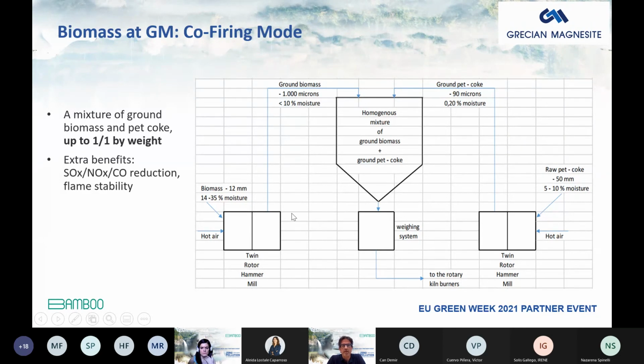Of course, the biomass must be milled in a mill with the introduction of hot air to reduce its moisture. And on the other hand, the pet coke, the unground pet coke, which also has a significant amount of moisture, is also dried and milled. The extra benefit of this partial replacement of pet coke, of course, is the reduction of other pollutants like SOx, NOx, and carbon monoxide, aiming, of course, to achieve the same flame stability.